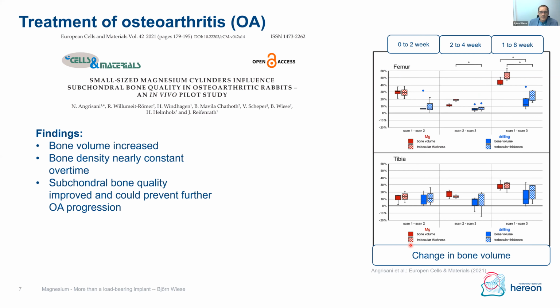The first findings are quite nice because we're already seeing that the bone volume of the rabbits in the femur and tibia increases, which are the red regions, for volume and the trabecular thickness from week 1 to week 8 after the operation. Compared to the blue ones, the drilled-only group, there's more or less no such significant improvement, especially in the femur. What we can see is that we increase the bone volume, but the density of the bone is nearly constant over time. So the quality of the bone is constant, but the volume increased.